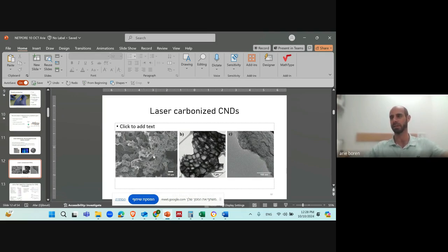You see that it's like a sponge. This is an SEM, and in TEM you see it's like honeycomb structure. And so it is very different in morphology than what I showed you before, the polyimide or graphene oxide. And the reason is we used the smallest building blocks that are possible out there.